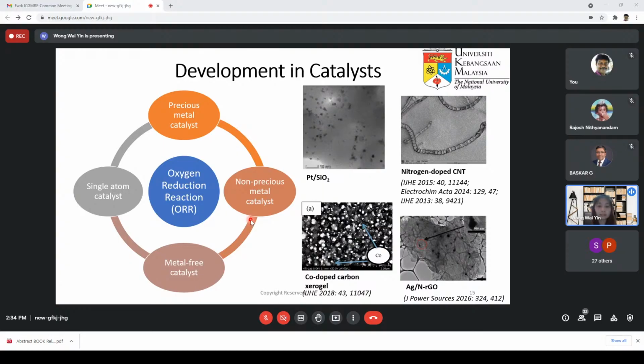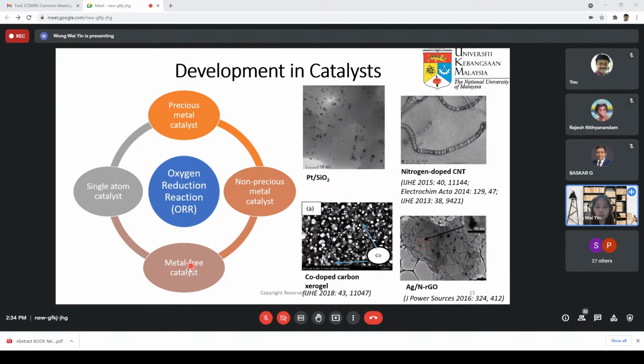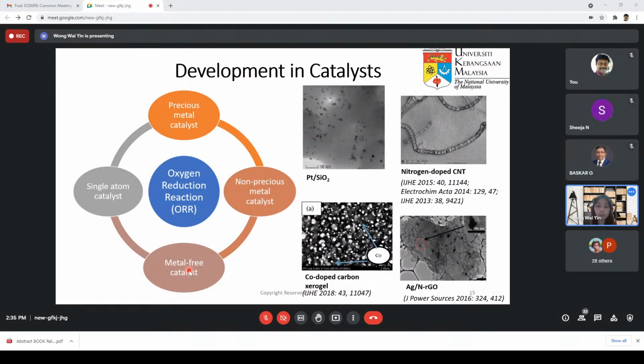To date, the most active catalyst that has been investigated is the iron and cobalt with nitrogen doped carbon catalyst. These have been extensively studied, although they have not achieved the performance of platinum, but they are in good progress. Then next, there's also study on the metal-free catalyst, which uses no metal, but actually uses heteroatom doping on the carbon itself. For example, nitrogen doped carbon, boron doped carbon, sulfur doped carbon. With this, they create the active sites for the oxygen reduction reactions. However, this catalyst is found not suitable to be used in hydrogen fuel cell, but is more suitable to be used in alkaline fuel cell itself.